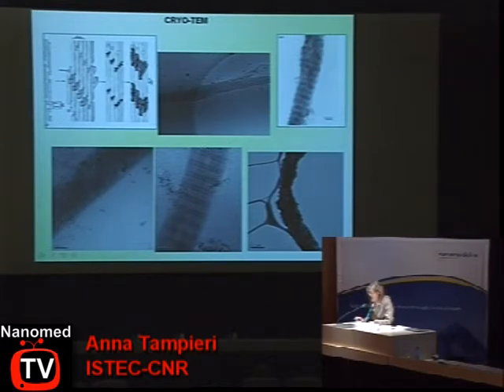We can also control, during the mineralization, the starting point of the mineralization, the space where the mineralization starts, which in the human case is in the gap between the collagen molecules. And so, using a small amount of polyelectrolytes like magnesium, which is extremely important in the physiological environment, also in doping HA, as I have shown you before, we can control the attachment of the mineral phase in the gap. We have a disturbing effect, as you can see in this picture, on the structurization of the collagen secondary structure. But this also prevents the detachment of the mineral phase, like in this image, and stabilizes the structure of the biohybrid composite.